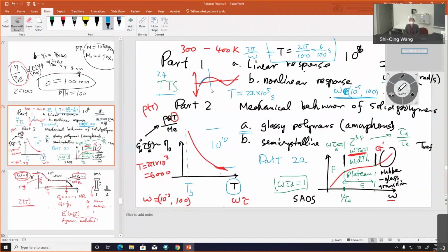But for accuracy, they tend not to do this and extrapolate the rest. See? Instead of using a whole cycle, let's say a quarter of a cycle should be enough. But instead, in commercial instruments, as far as I know, they usually take several cycles. So instead of 6,000 seconds, it could be multiple of that, let's say 3 or 4 of that. Wow. Pretty soon it's several hours.